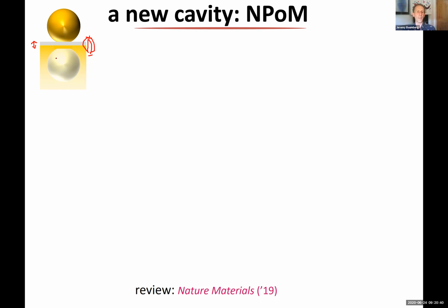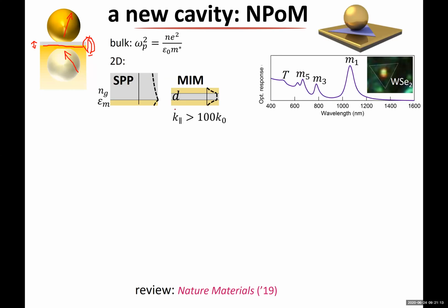So when this gap is very small, it turns out that any dipole that exists inside the nanoparticle will also create an image dipole below it. So we can actually look at this system electrostatically. We don't really have to understand that the light is fluctuating at enormously high frequencies, but we can just treat the system like that. So this looks like a nanoparticle with an image nanoparticle sitting below it. And indeed, all of the optical modes look exactly like that. They look exactly like a dimer, but they're coupled a bit more because there's a bit more surface here.